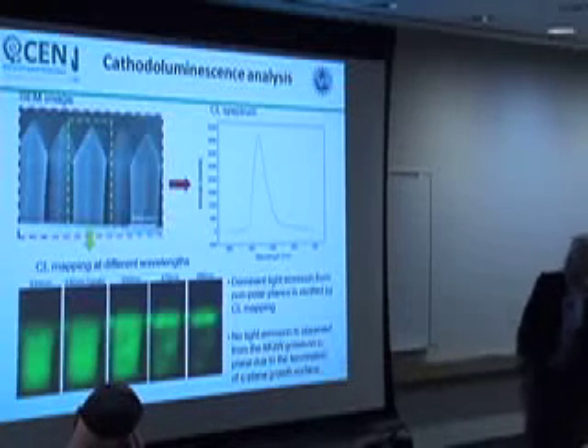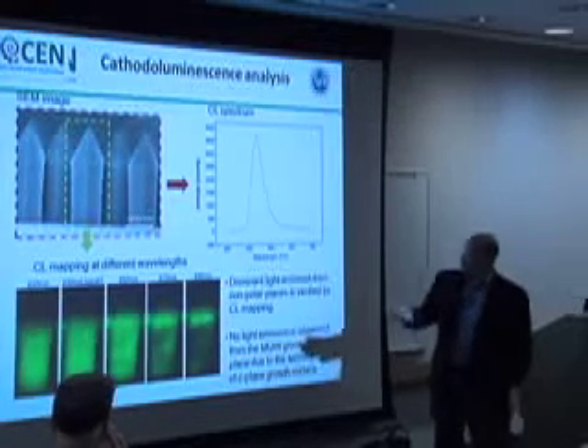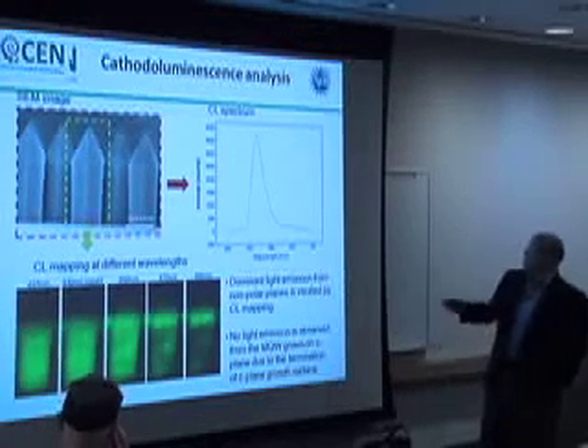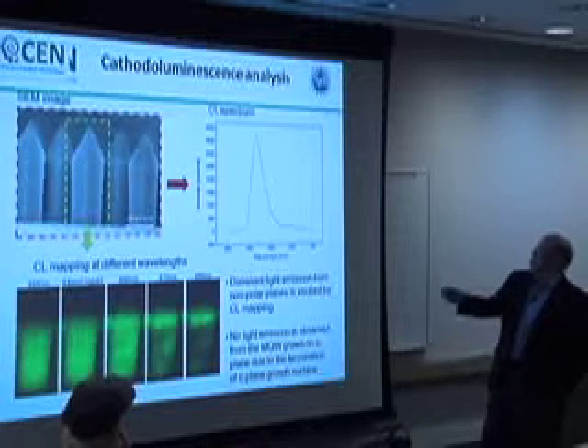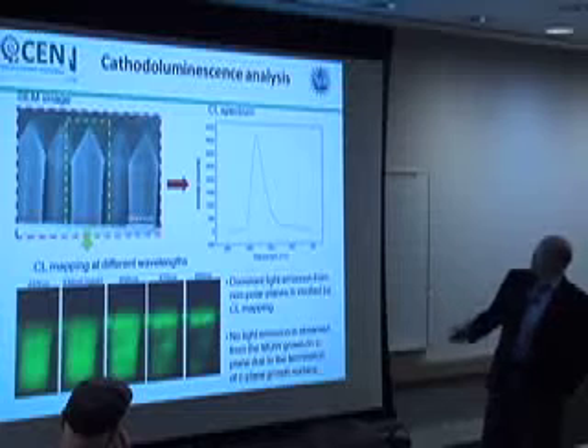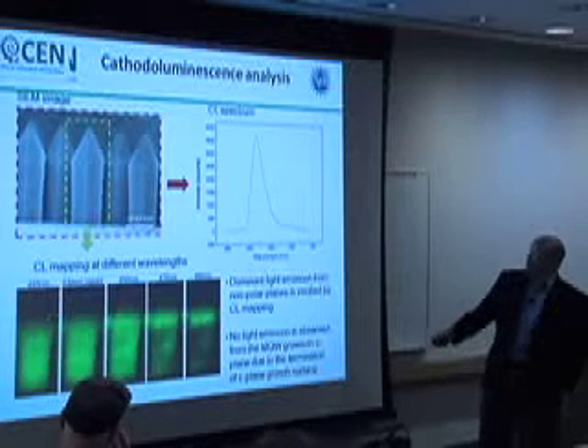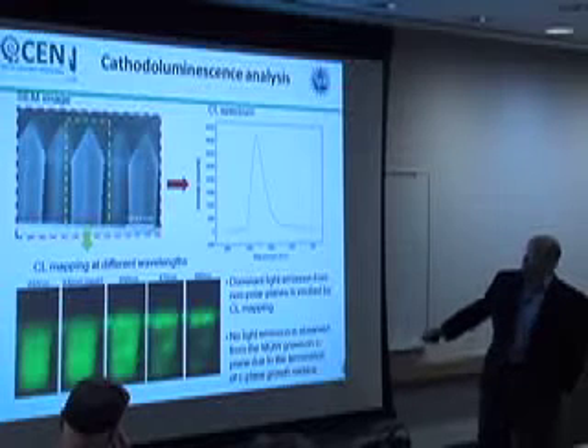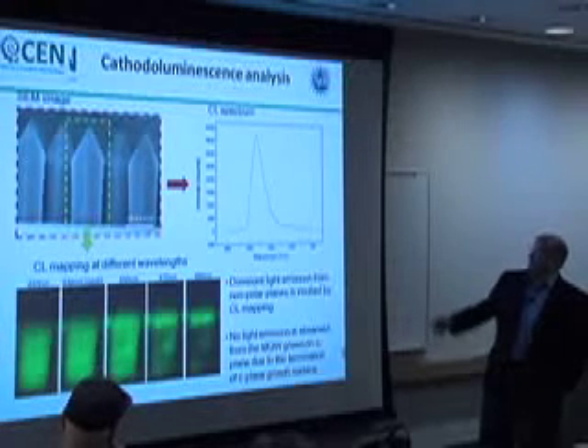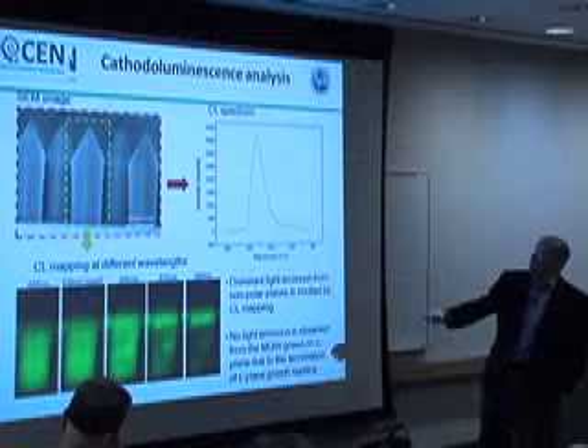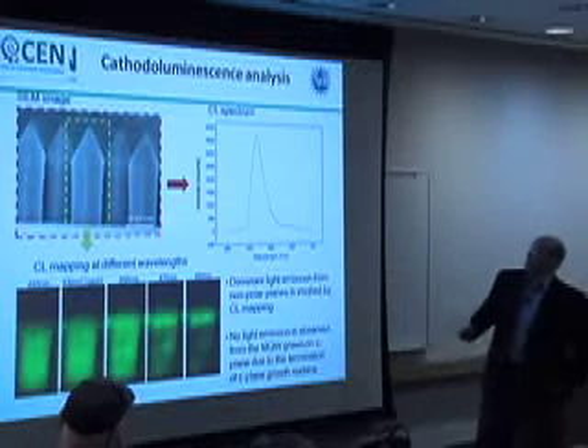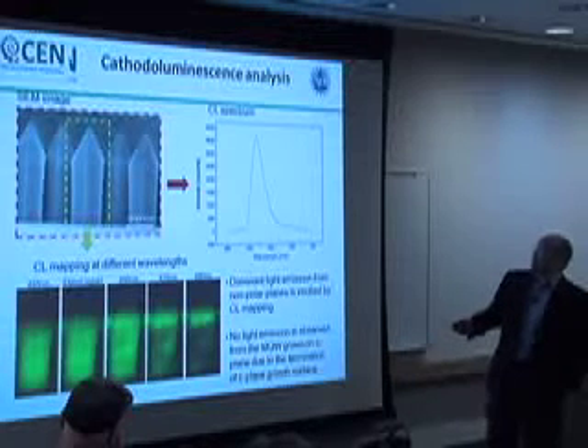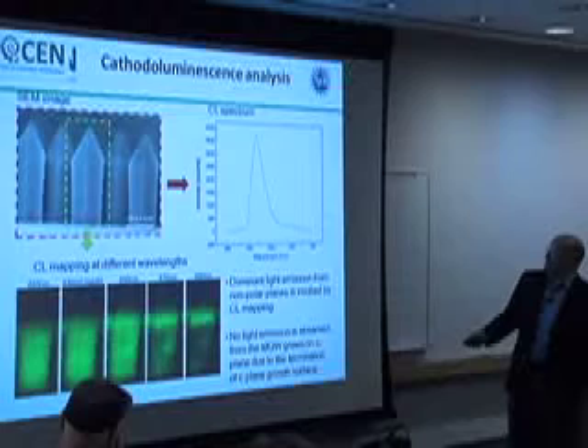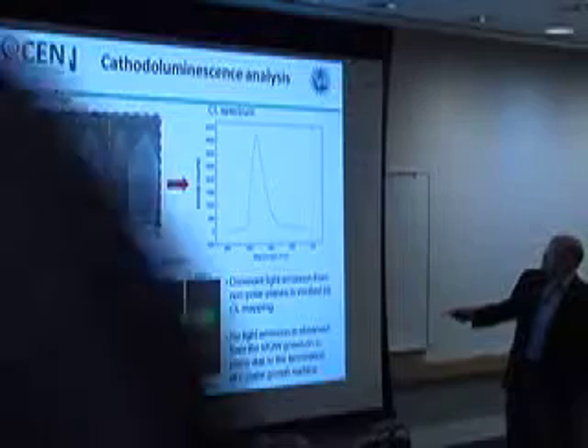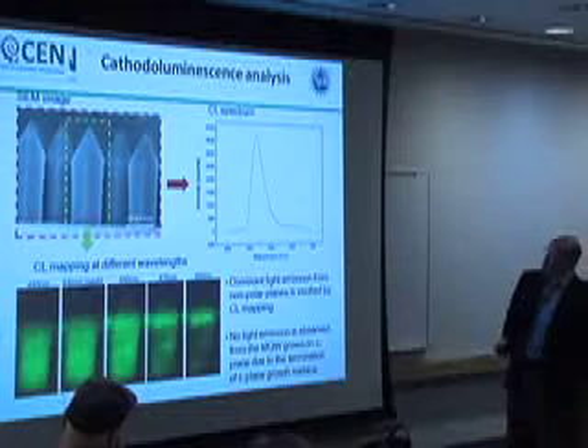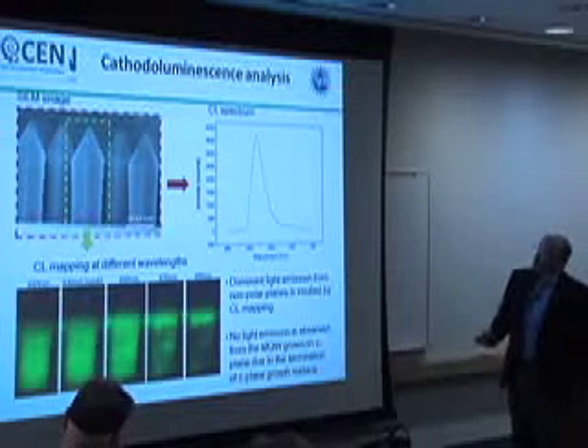So we've looked at those nanowires and looked at cathodoluminescence. This is one that, if you did PL or CL on it, would emit at about 450 nanometers. And what we see is that the majority of the sidewall emits in the range of 430 to 450. Only the region right around the collar here, where the growth rate was greater, the layers are thicker, and perhaps the indium concentration is higher, do we see longer wavelength growth that accounts for this extra peak here in the emission spectrum. So we're pretty happy with that.